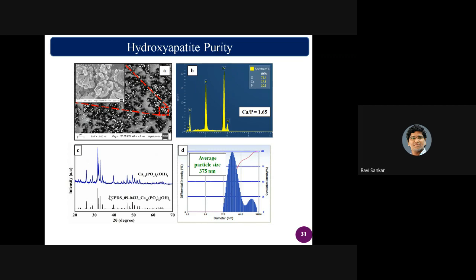At the same time, you also have to maintain the calcium to phosphate ratio. Assume that you have a very good amount of calcium but a very small amount of phosphate. In that circumstance, it will be very problematic because osteoporosis and other things will come. So you need to maintain not only the purity, you should also maintain the calcium to phosphate ratio. The calcium to phosphate ratio should be in the range of 1.65, or you can also go for 1.64 to 1.68. So we are on the edge of 1.65.